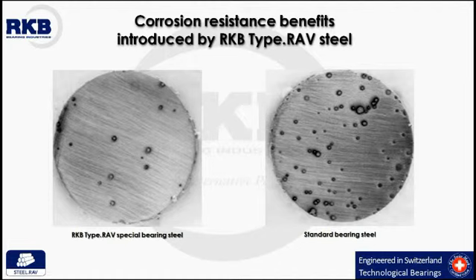The high corrosion resistance of the RKB Type.RAV steel was proved in a sodium chloride solution immersion test. As it can be easily noticed, there is excessive rust on the standard bearing steel surface compared with the RKB Type.RAV steel sample. In fact, standard bearing steel contains coarse eutectic carbides that act as crack initiators and reduce chromium content in the martensite matrix. On the contrary, the RKB Type.RAV steel has no eutectic carbides, but consists of fine dispersed carbides and strong martensite that improve resistance to corrosion.